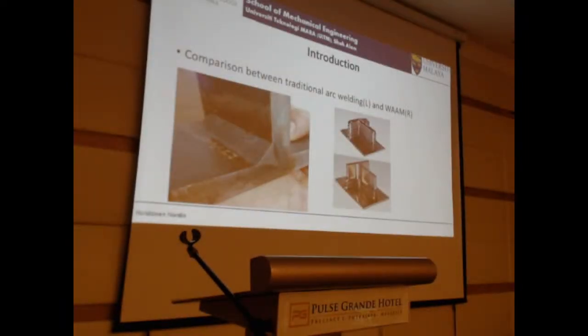Okay, so there are three pictures here. The one on the left is a T-joint, that is a conventional welding specimen. And on the right there are two pictures, that is the product of wire arc additive manufacturing. One thing you can see is that in conventional welding there's very little filler wire. Basically the metal that you deposit onto the substrate or another structure is smaller than the base metal.